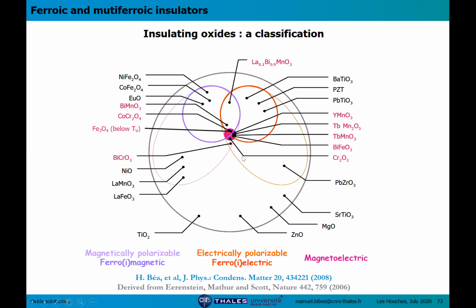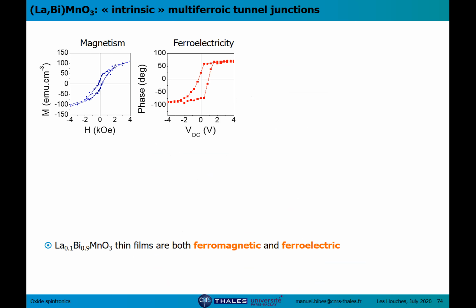This is a Venn diagram that shows, let's say, magnetically polarizable compounds and electrically polarizable compounds. And here you have ferromagnets, here you have ferroelectrics, and there are extremely few ferromagnetic ferroelectrics, okay? So bismuth manganite was believed to be one of them. Cobalt chromite is also one at low temperature, and below the Verwey transition, Fe3O4, which is a well-known ferromagnet, is also ferroelectric. So we work with lanthanum-doped bismuth manganite.